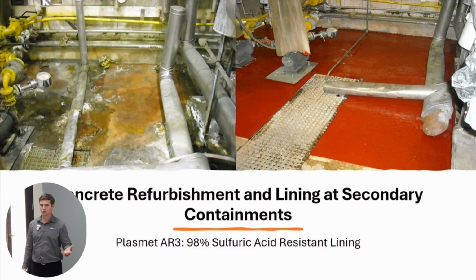Concrete. So we talked about concrete in some of the Q&A before. Sulfuric acid. This is one of my first inquiries 16 years ago. I went out there and I looked at this. You can't tell, but this is just mush. I mean, it went straight down to the sub-base. We had to take all that out. We used epoxy polymer concrete to fill in the cavity underneath this pump base. The reason why I use the polymer concrete, other than it being more corrosion resistant, is that you can overcoat it with a compatible coating. You don't have to wait 28 days like you would with concrete. And then we coated it with the AR3, the Plasmet AR3 98% sulfuric acid resistant coating.